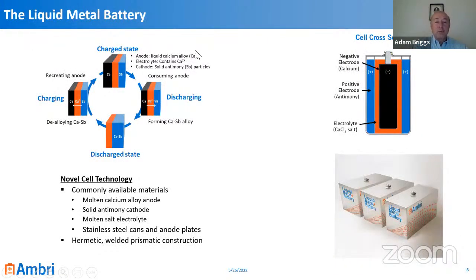And the way the chemistry works is you can see in a charged state, essentially you have calcium and antimony separated by an electrolyte. And as you discharge the battery, the calcium gives off 2 electrons, and calcium 2 plus ions flow across the electrolyte to form an alloy with the antimony at the cathode area.